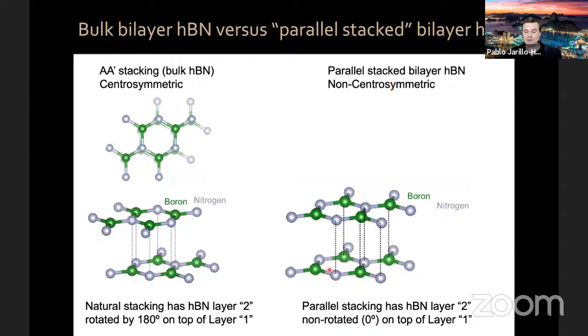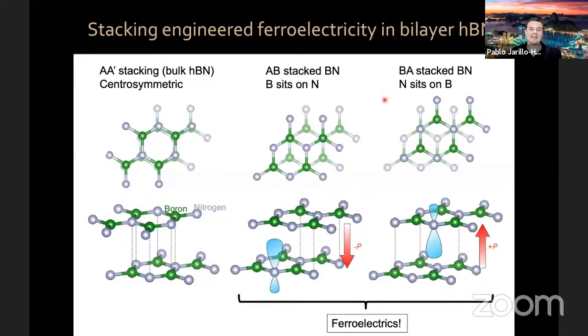Now, this configuration with nitrogen atoms on top of nitrogen atoms, boron atoms on top of boron atoms is extremely uncomfortable for the hexagonal boron nitride. So the system, parallel stack boron nitride, decides to go into an AB or BA stacking configuration, where the boron atom sits on top of the nitrogen, or the nitrogen sits on top of boron, but with empty spaces in some of the locations. This leads to a finite permanent dipole moment, which is opposite for AB and for BA. But for either configuration, you have ferroelectricity. You have an electric dipole moment, which is permanent there.